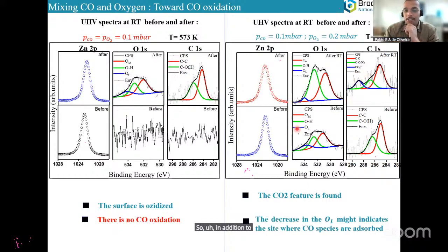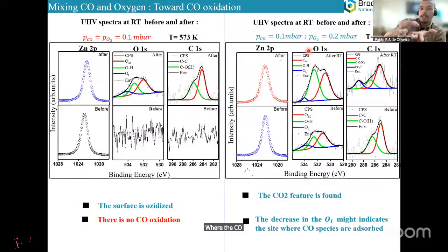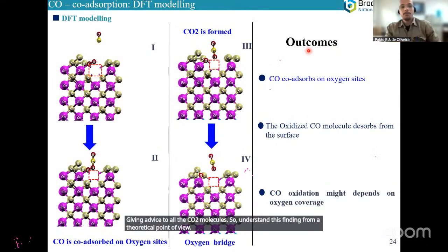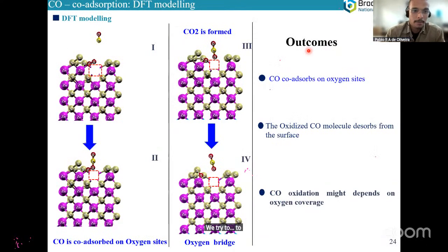So in addition to the CO2 feature, we might suppose the place where the CO is sticking on. So this experiment is suggesting to us a Mars-van Krevelen-like mechanism where the CO is anchoring on the oxygen site and then promoting the separation of the oxygen at the surface, giving rise to a CO2 molecule.